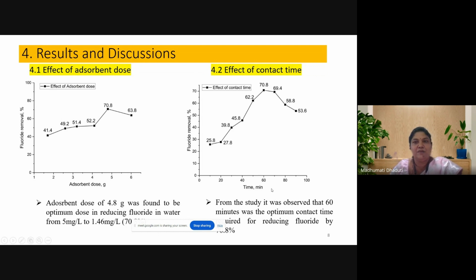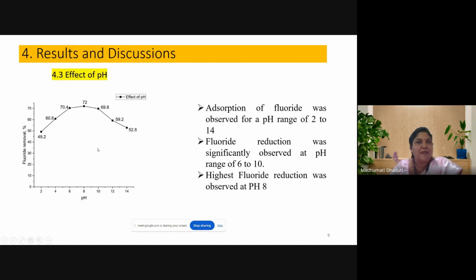And from the study of the effect of contact time, it was observed that 60 minutes was the optimum contact time required for reducing the fluoride by 70.8%. And when it was tested for the effect of pH, it was observed that the fluoride removal was significant in the pH range of 6 to 10, whereas the highest reduction was observed for the water with a pH value of 8.